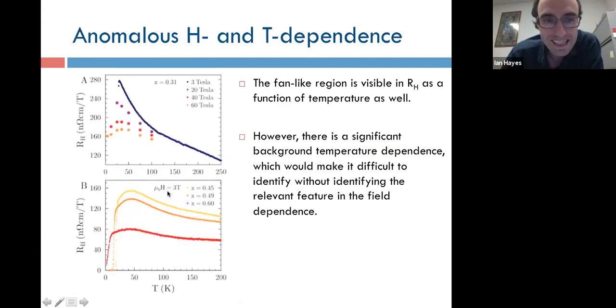And you can see this in the temperature dependence of the Hall effect as well, but it's a little trickier because of the background. This is one thing I really want to highlight about this use of the field dependence to characterize the strange metal behavior, is that it allows you to make cleaner determinations about which part of the Hall coefficient is actually correlated with superconductivity and with proximity to the antiferromagnetic phase.